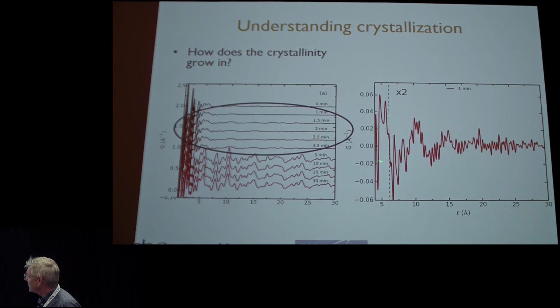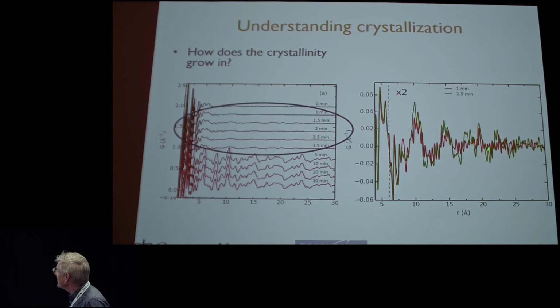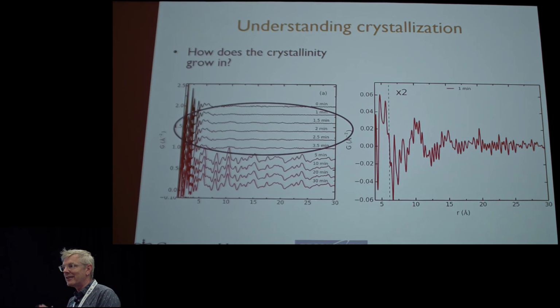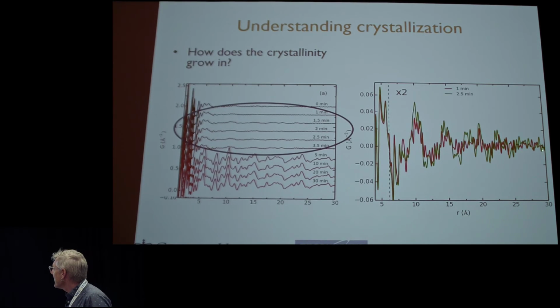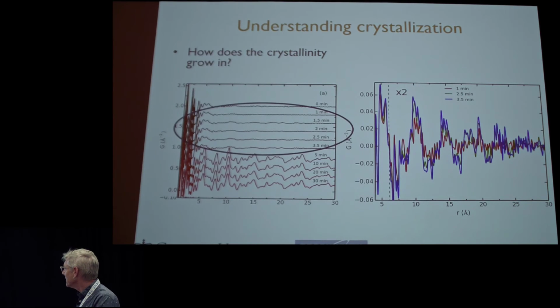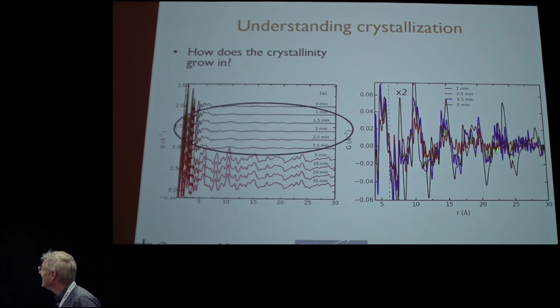But what we can do is we can look at the signal here, we can blow it up. So this is the 1 minute signal, and it's very noisy, but there's actually features there. And then 2.5 minutes, what we can see is the features are kind of growing, and 3.5 they're growing. And what you can also see is that this area is flat, so this is telling you the size of the nuclei. And then you can see the peaks are appearing at higher R. So the nuclei are growing, but they all have the same structure. But when you recrystallize, if you look carefully, this is the recrystallized form, and actually the peaks are in different places. So the first thing that forms is actually a different crystal structure from the final thing that recrystallizes out.